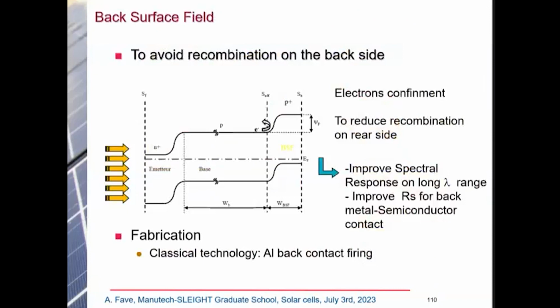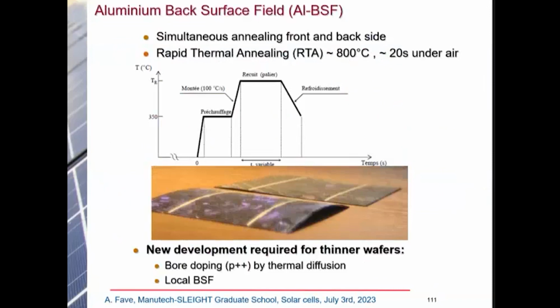So that's why, when we deposit aluminum, we have a high temperature step in order to make diffusion of aluminum into silicon and to have this electric back surface field here, to avoid the electrons going to the surface. Okay. So they will not be recombined at the back surface. However, to decrease the cost, you decrease the thickness of the wafer. And when you decrease the thickness of the wafer and make this high temperature firing step, because of different values of thermal conductivity of silicon and aluminum, you can observe this bending of wafers.